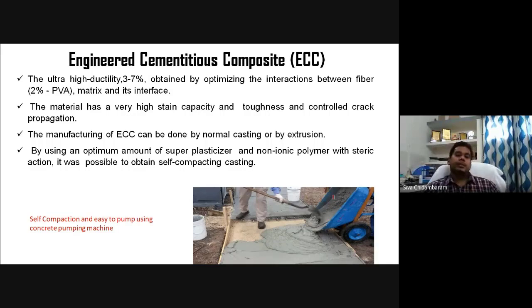Next one is engineered cementitious composite, developed by Professor Victor Li, in which he has used 2% polyvinyl alcohol fiber, fine admixtures such as fly ash, GGBS, microsilica, etc., cement, sometimes sand, sometimes no sand, and then fiber, water reducing admixtures, and high range water reducer admixtures. Water reducing admixture means, for example, if I want to use a water-cement ratio of 0.25 instead of 0.5, then I have to use water reducing admixtures. Then a high range water reducer also has to be used, to disperse the fiber so that fiber segregation does not happen. So many things are there.